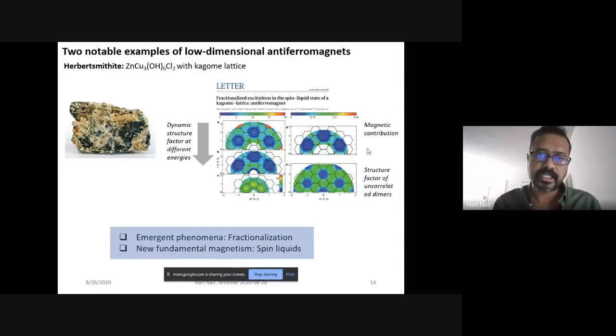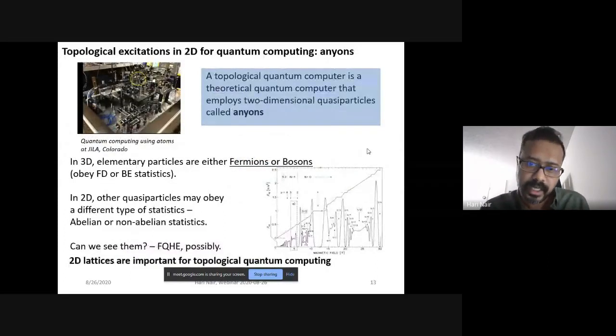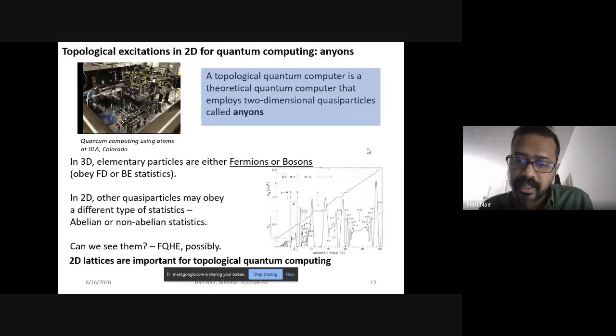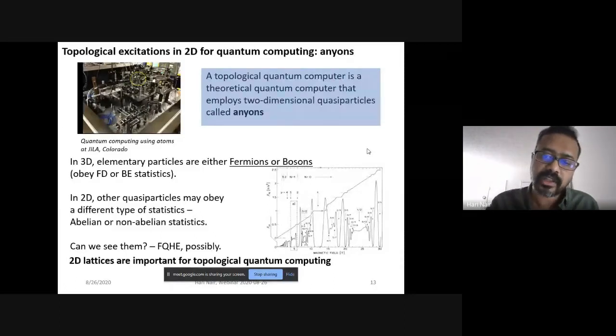And why fractionalized? Fractionalized because you see here, the image on the right bottom is nothing but the observation of the fractional quantum Hall effect. It's a plot of resistivity, rho xy, in a two-dimensional plane, on the y-axis, and a magnetic field in Tesla on the x-axis. You see that sharp jumps occur at fractional values, and those fractional values are not values of the magnetic field, but fractional values of electron filling in the material on which they measured the resistivity.